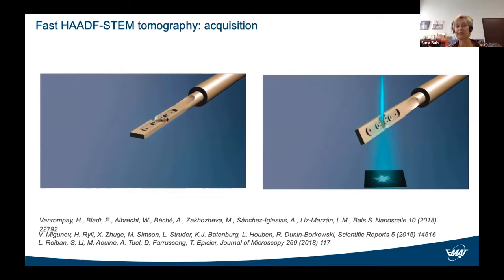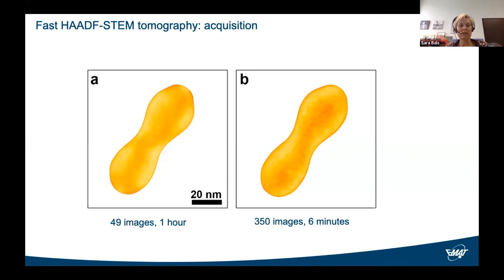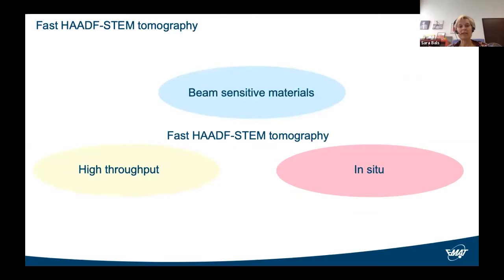In order to test the reliability of this approach, we made a comparison, which is illustrated here. So this is again a gold nano dumbbell. On the left, you can see the result after acquiring 49 images conventionally in 1 hour. And on the right, you can see the result of the fast tomography, where 350 images have been acquired in about 6 minutes. You can see that there's a very good agreement between both reconstructions, and that means that the